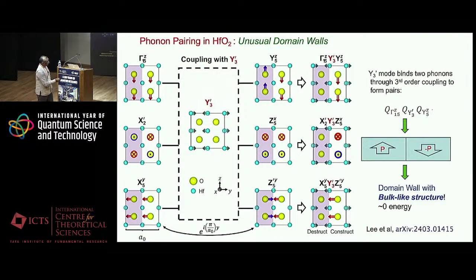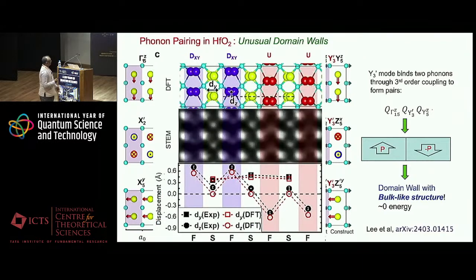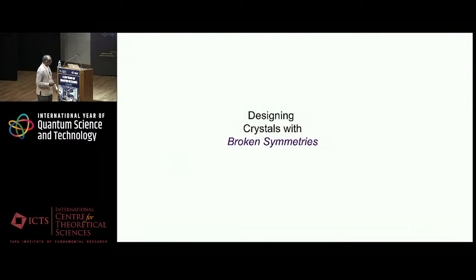And as a result, what we have shown in detail is that the domain wall in this material, which separates up and down dipolar polarization, is identical in structure to its bulk. You know, the bulk and domain wall are more or less structurally similar. And there is an experimental proof now from the Korean group, where they have measured atomic positions using very high resolution microscopy, and they verify basically this prediction we have that domain walls are identical to the bulk, like boundary and bulk are identical. Okay, so I will now switch gears and move to coupled quantum classical degrees of freedom.